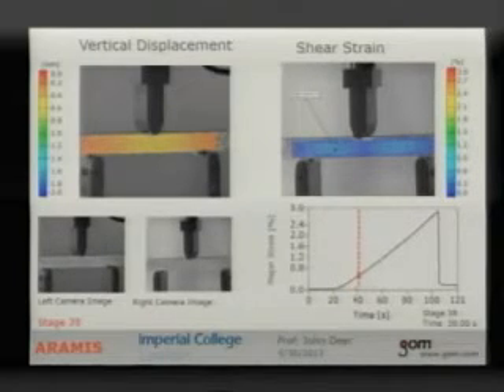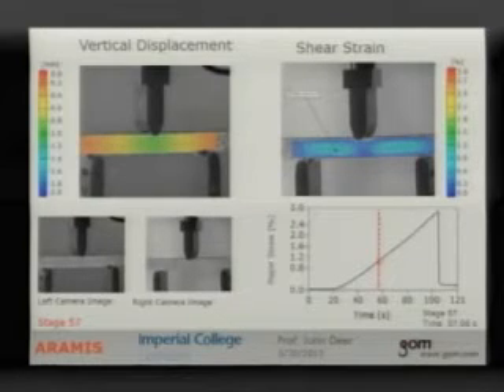So you're starting to see some light blue either side of the roller, and that will, under the roller itself, there is no shear, shouldn't be, but over to either side, between the outside roller and the central roller, you're starting to pick up those regions of high shear.